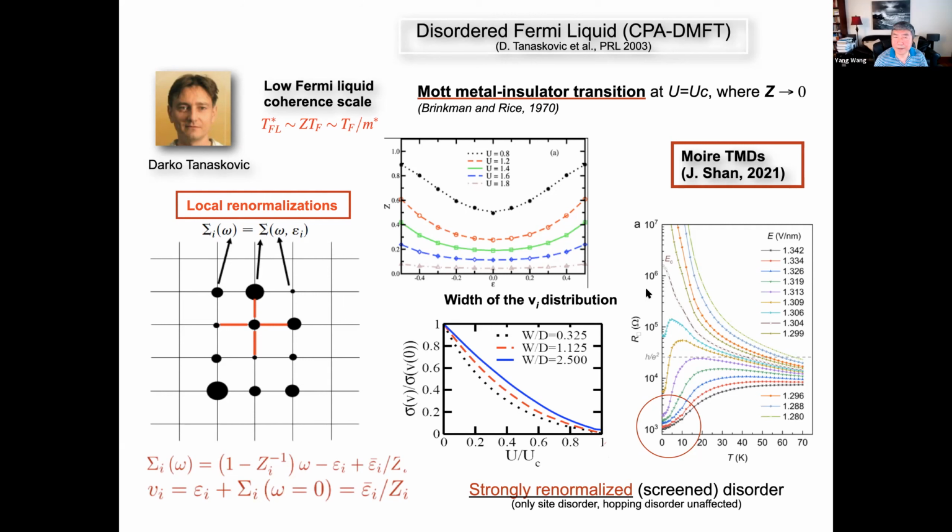We're talking about chemical disorder, right? This is site disorder. So I just took a broad flat distribution of site energies, which, for example, in the calculation that Maria did, are renormalized by the Madelung effect, and so we do get, even in her calculations, that these site energies are broadly distributed. So I just took a featureless distribution to start with, and then I'm approaching the Mott transition by cranking up Hubbard U.